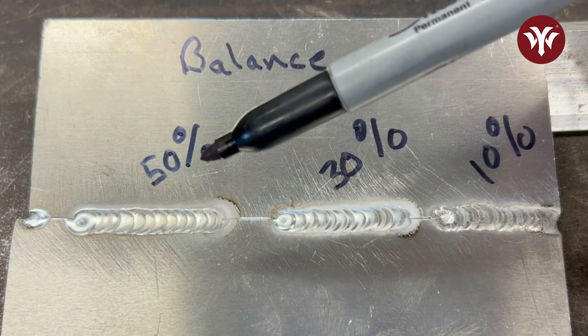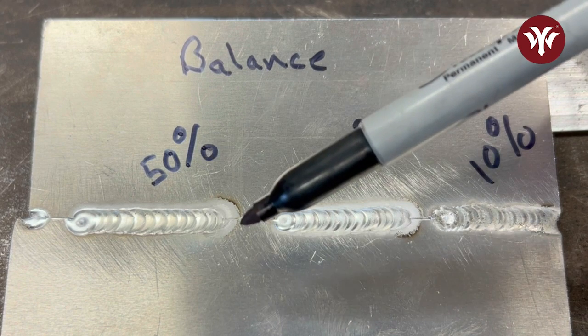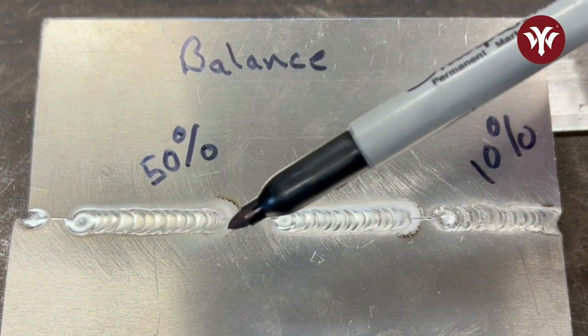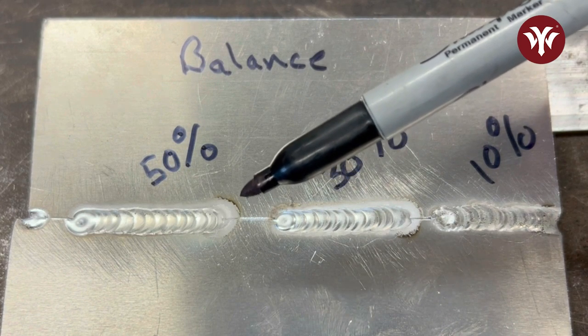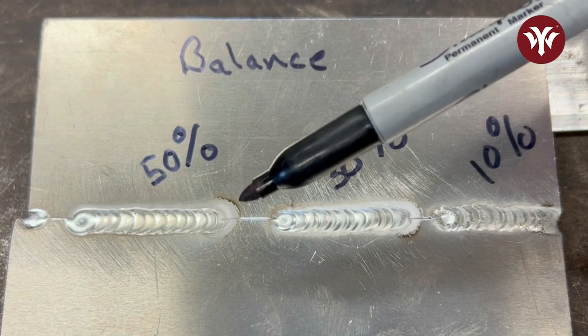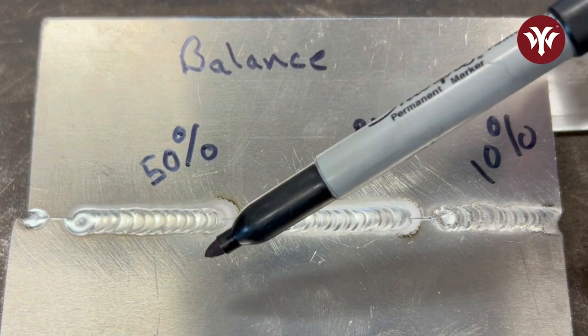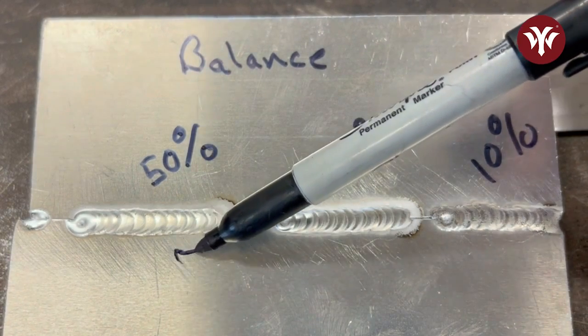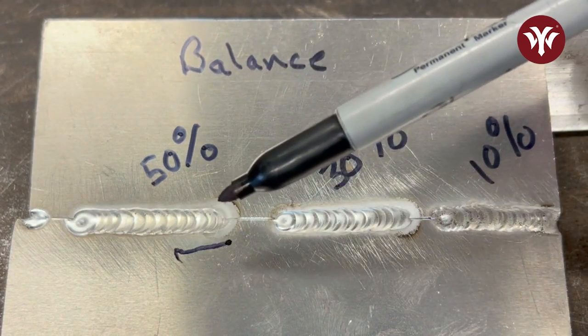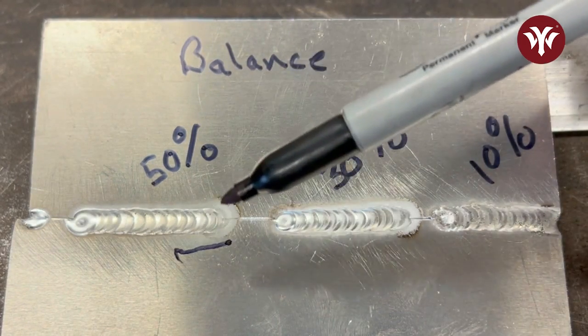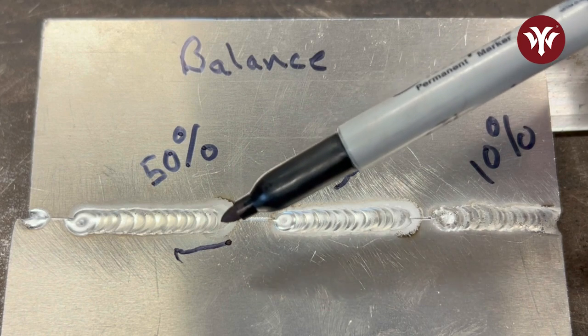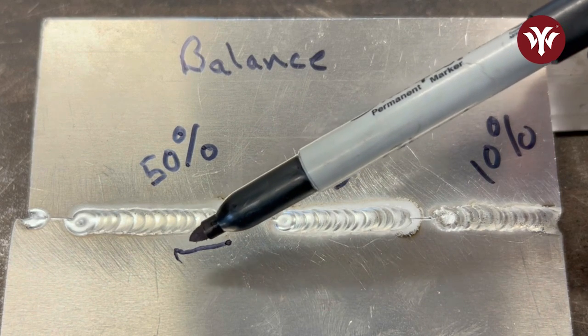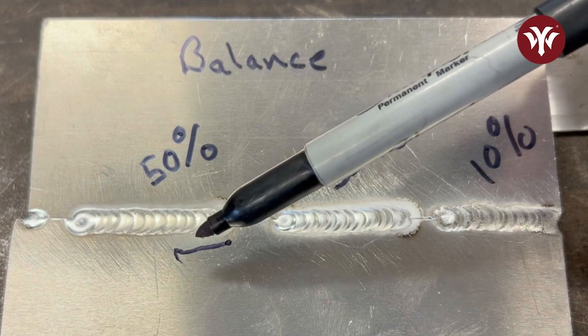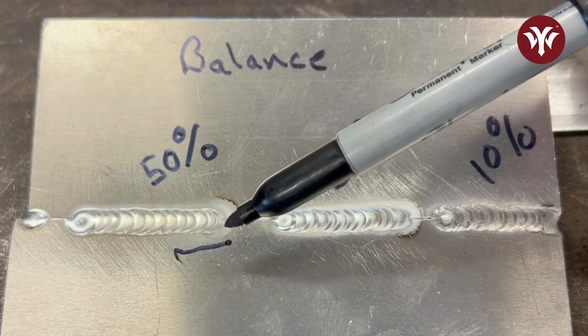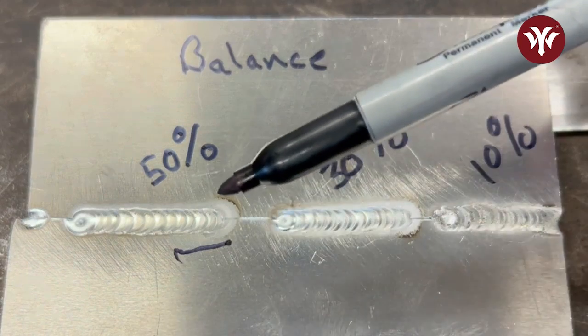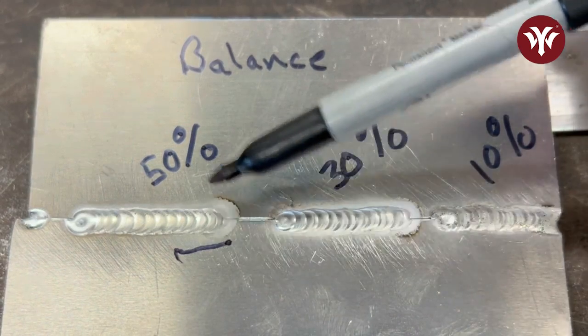Now here is 50%, and the balance does go higher than that. The actual effective cleaning zone didn't get much larger, so I think we were probably maxed out to the shielding gas coverage we had. If you wanted this etching to come out even farther, like out to here, which there's not really a big reason to, the cleaning action will only take place inside of the argon shielding gas. So I probably didn't have much gas coming down over here because of the size of the nozzle I was using. So that just shows you how nozzle size does play a role in cleaning action.